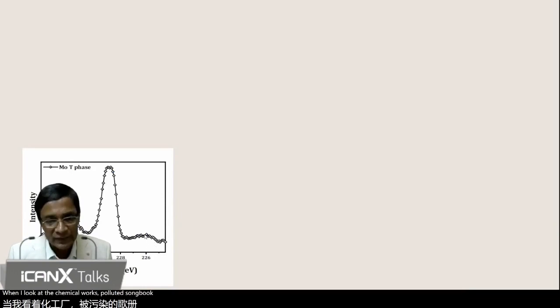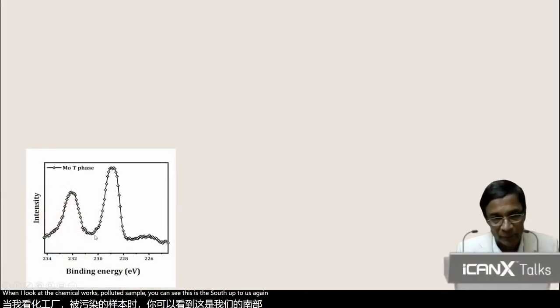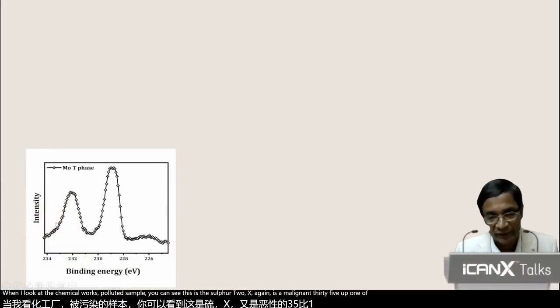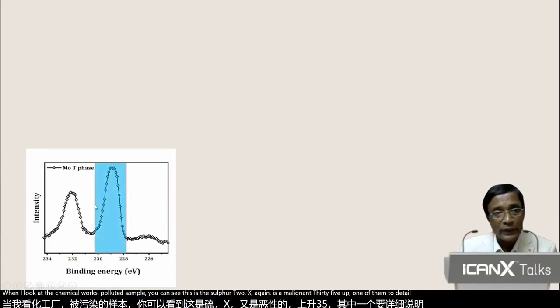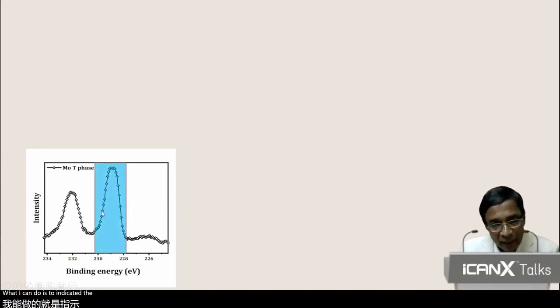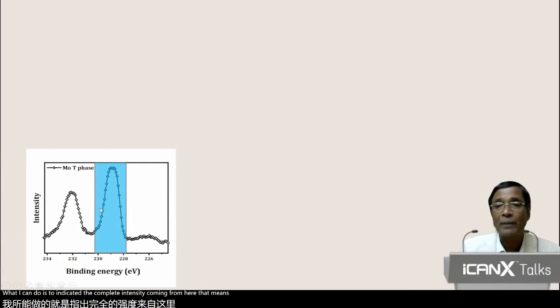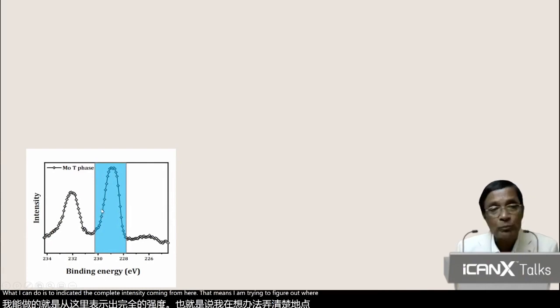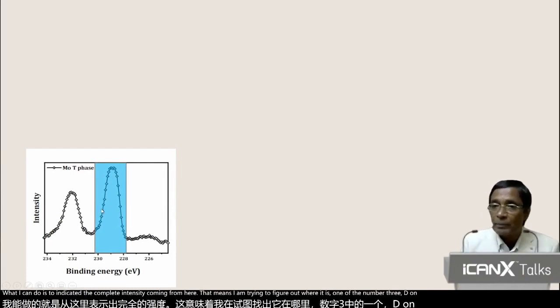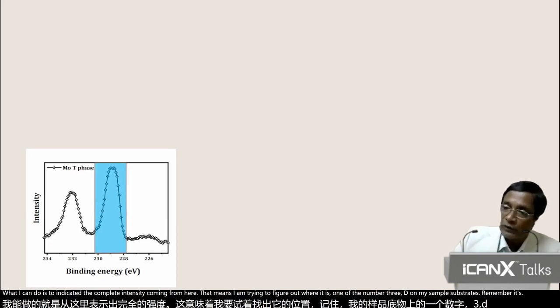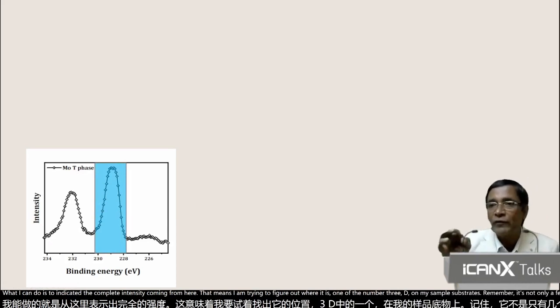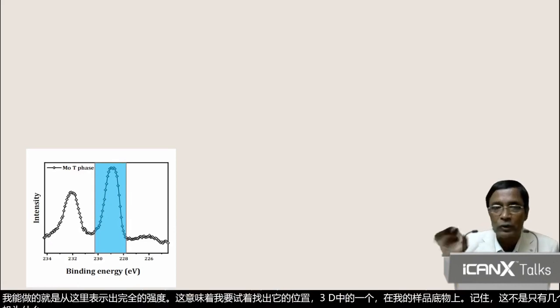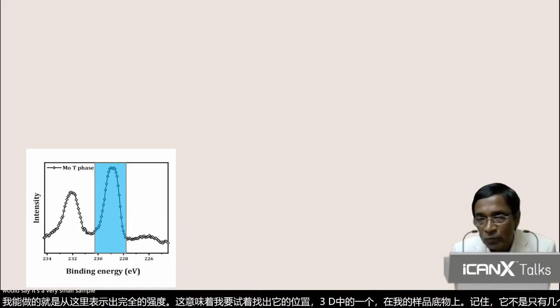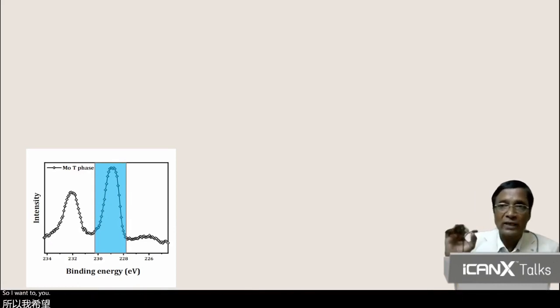When I look at the chemically exfoliated sample, you can see this is the sulfur 2s again. This is the molybdenum 3d 5/2, molybdenum 3d 3/2. What I can do is integrate the complete intensity coming from here. That means I am trying to figure out where the molybdenum 3d is on my sample substrate. Remember, it's not only a few layers thick, these are also few-micron-wide samples. So it's a very small sample.